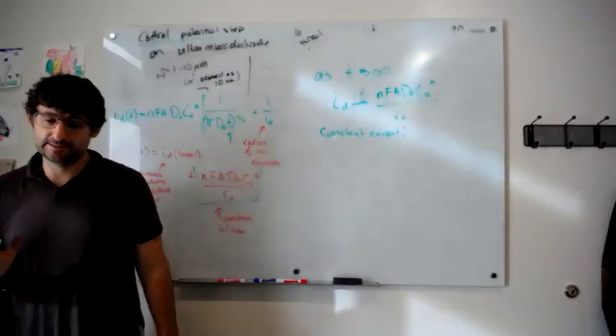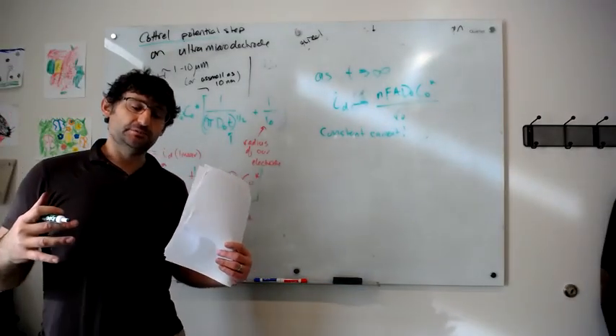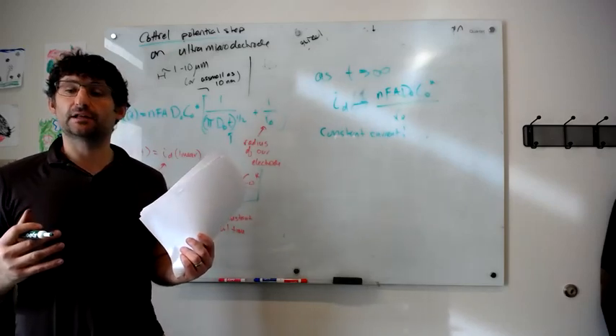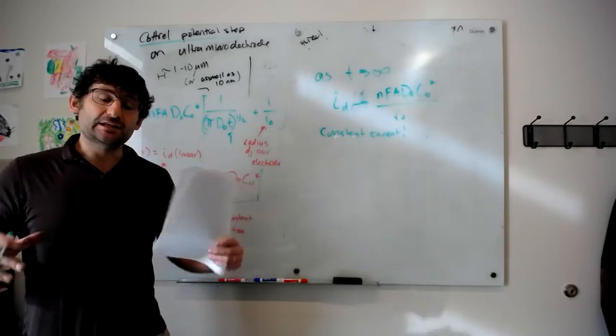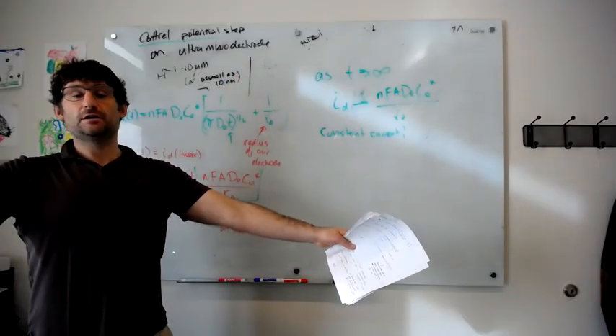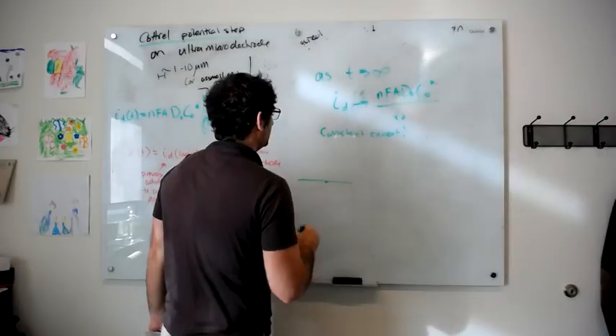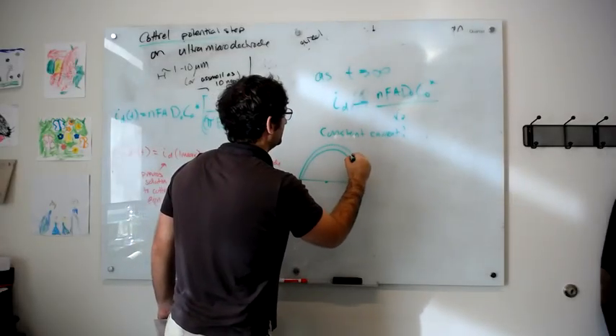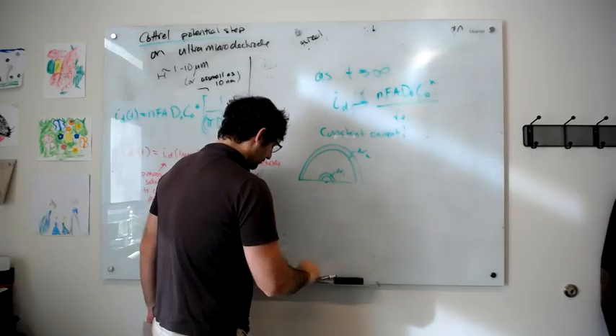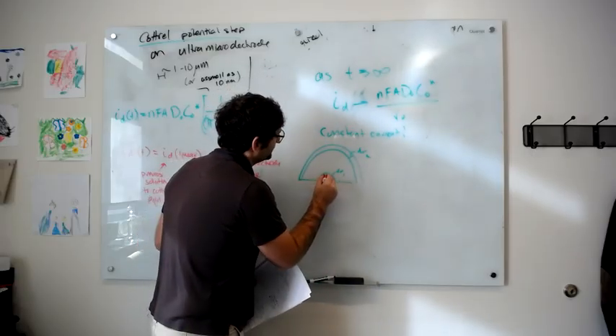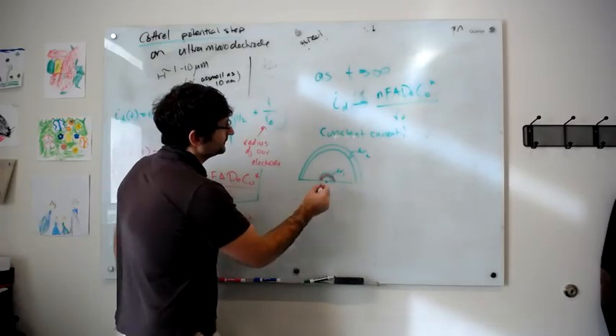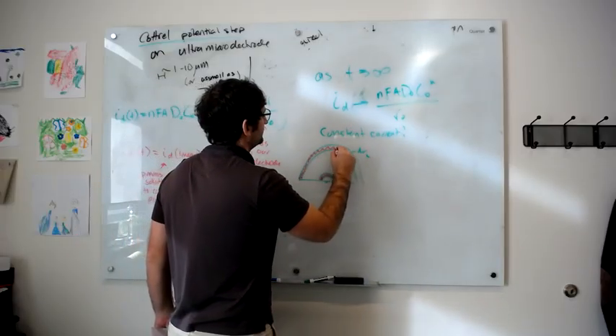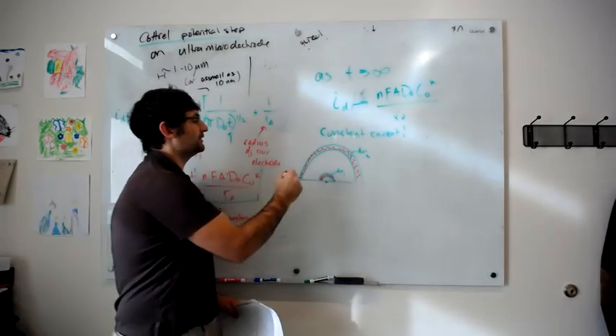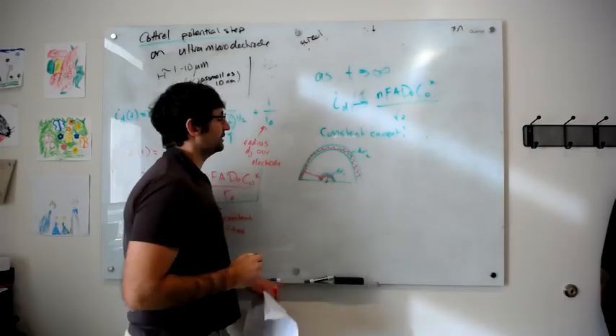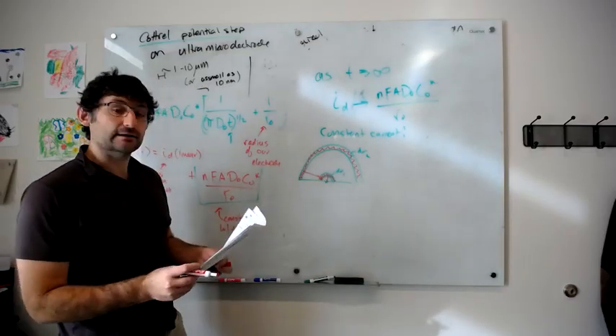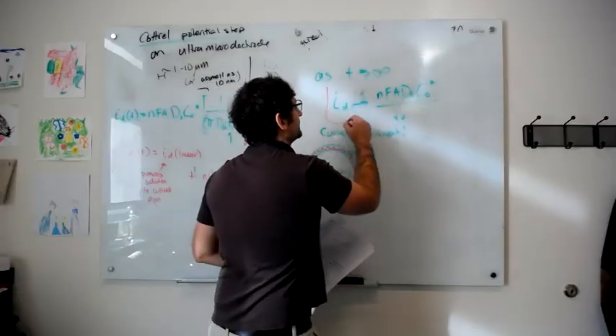And that's precisely because, if you think about it, there's a competition between pulling species from further and further away from the electrode with longer and longer time, and the fact that you have more volume to pull species from. If I'm pulling stuff from some element dr, in short time I only have this volume element to pull species from, but the same dr at longer times gives me many more species to collect, but they have to diffuse further. So those two effects exactly compensate for each other and give rise to this constant current.